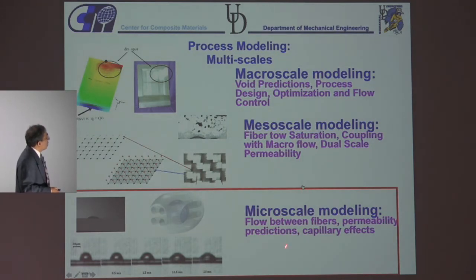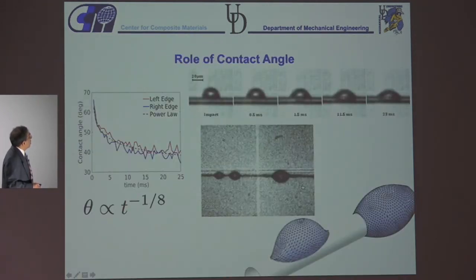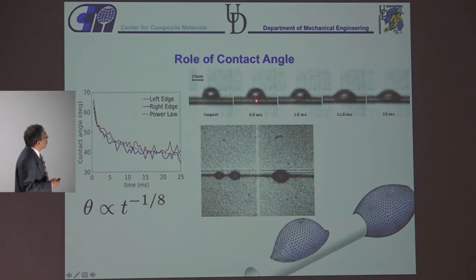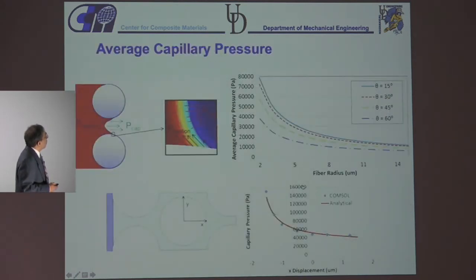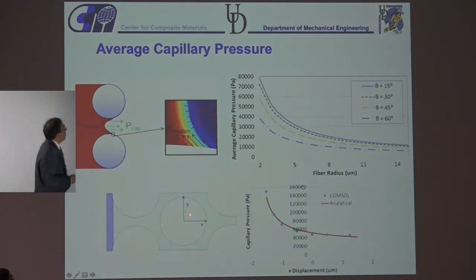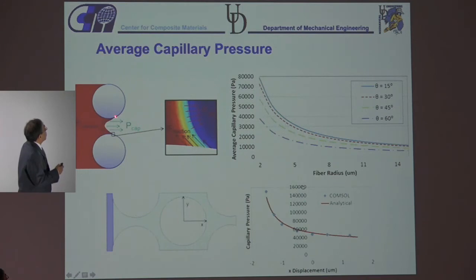Okay, so now on the microscale level, what happens is usually you put a drop of resin on a tow, and this contact angle plays an important role in how quickly this is going to go inside the tow. You can measure the contact angle very easily, and there is some law of what happens at that level. So one thing to mention is that the capillary pressure between the fibers is only important where you have vacuum, because capillary pressure is very low. It's usually about 1/10 of the atmospheric pressure. So it is only going to play an important role near the flow front.